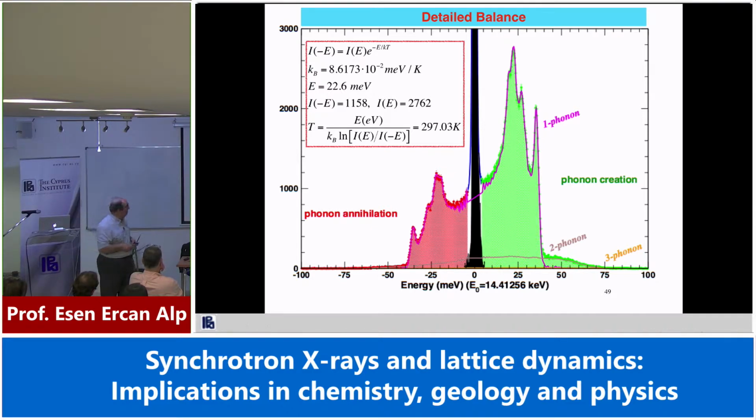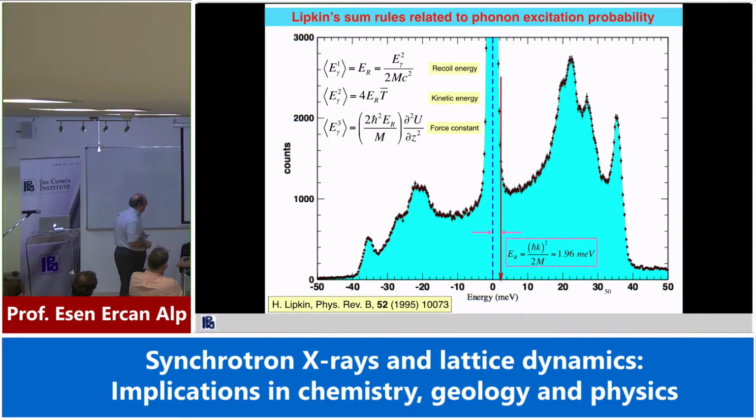Now you can say, to measure room temperature you need a $1 million instrument and a $1 billion machine. That doesn't make sense. But if you have a sample in a diamond anvil cell sitting at 3 megabar pressure and 2000 degrees, and you want to know what the temperature is on a nanogram or picogram material, there is no method to measure temperature except this detailed balance. Right? So we use this to measure the melting point of iron and iron minerals inside the Earth at temperatures and pressures commensurate with the core of the Earth. Right? So it's used for that.